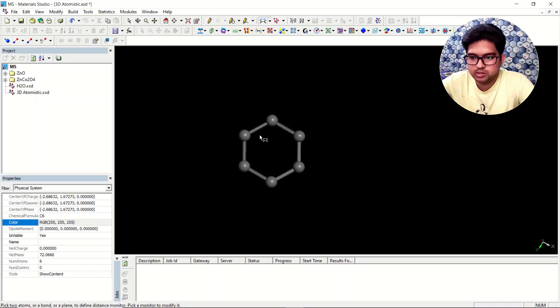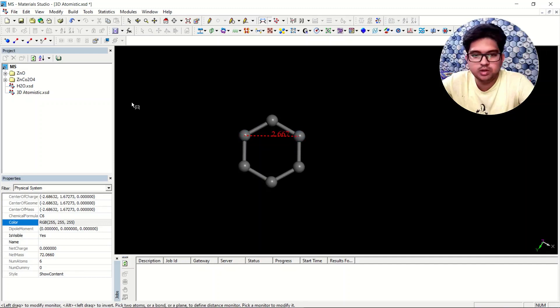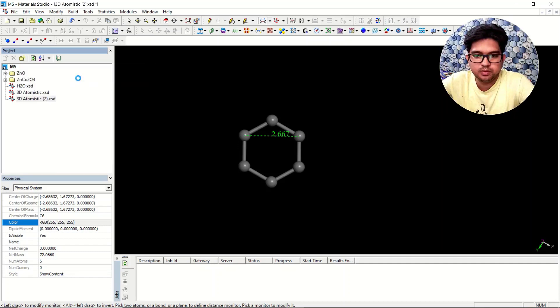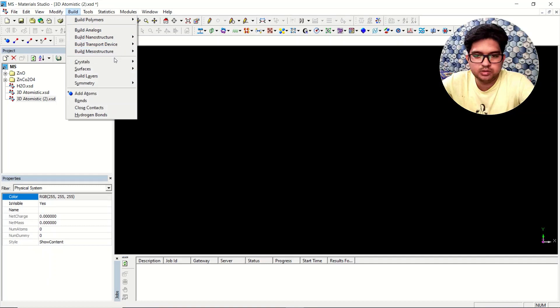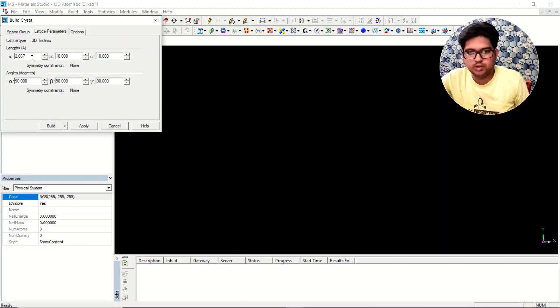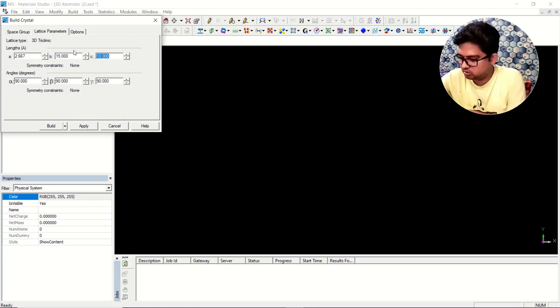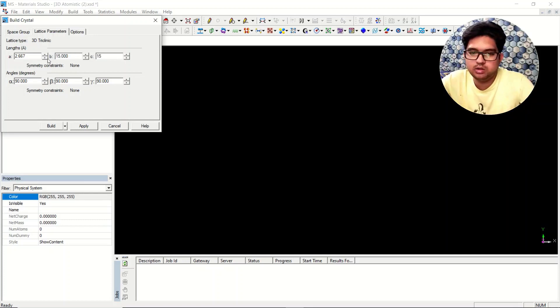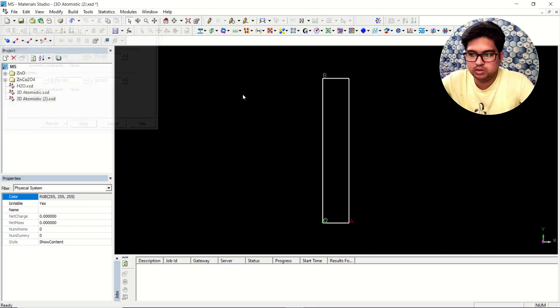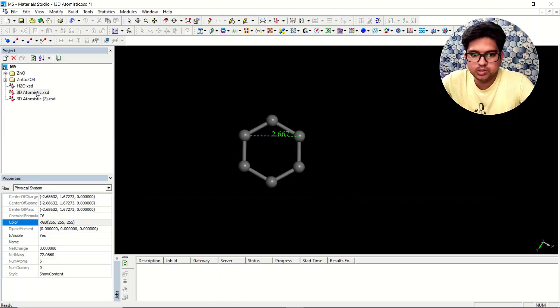We need a crystal lattice system. I'll note down the edge length — this distance is 2.667 Å. I'll build a lattice with an edge length of 2.667 Å, and keep the second and third dimensions at 15 Å so there is no interaction between layers, making this effectively a one-dimensional polymer.